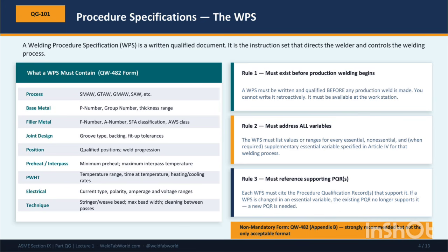Rule 2. The WPS must address all applicable variables: essential, non-essential, and supplementary essential when toughness testing is required. You cannot selectively fill in the easy ones and skip the rest. Rule 3. The WPS must reference the procedure qualification record, the PQR, that supports it. If you subsequently change an essential variable in the WPS, the existing PQR no longer supports it and you need a new PQR. The link between WPS and PQR is formal and must be documented.